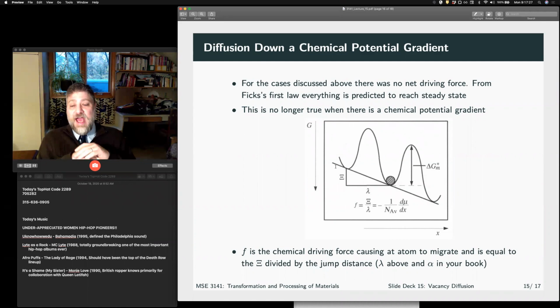That's, of course, in the absence of any chemical potential gradient, and in that case there isn't a driving force for net migration. It's just that the potential is uniform everywhere, and in regions where there is a large composition, you have more hops than a region where there is a low one.